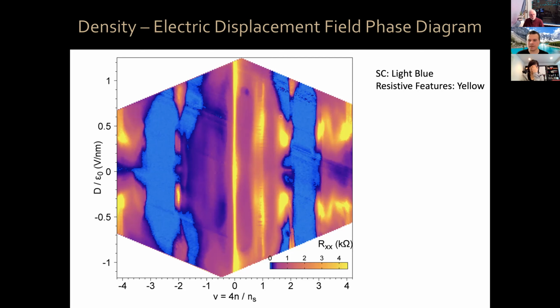Now, highly resistive features are in yellow, for example, at the charge neutrality point, and then close to some other integers. Let me concentrate now. Depending how you look at this diagram, you can focus on the symmetries or on the asymmetries. Let me focus first. As you can see, there is top-down symmetry. This means the system is quite symmetric with respect to displacement field. You can see these features. They're also here. These features are also here. These features are here and here. They're quite symmetric with respect to displacement field, top and down.